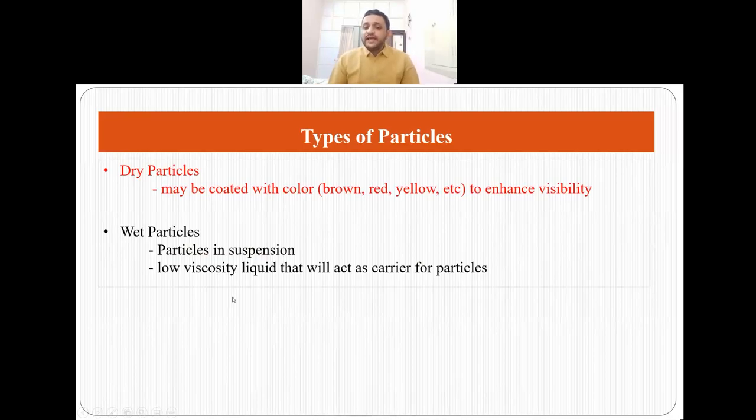And this liquid will act as a carrier for particles and it will ensure uniform distribution of particles. So mostly wherever possible, we use wet particles and we avoid dry particles. But if it is a rough surface, then we have to go for dry particles. We cannot use wet particles on a rough surface because our results will not be good. And on rough surfaces, we go for dry particles. But mostly we try to go with a wet suspension because uniformity of particles is more if we use wet suspension.